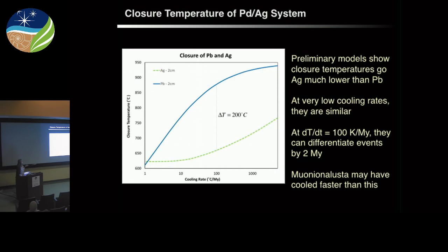And we have some idea of what's happening with lead. It's closing at a high temperature, potentially close to the initial crystallization, or the solidus, of iron sulfide. And then the palladium-silver system is actually closing a little bit later than that, at a lower temperature. And the idea is eventually, if we have high enough precision data, we can start to untangle all of this. So here we have cooling rate versus closure temperature.